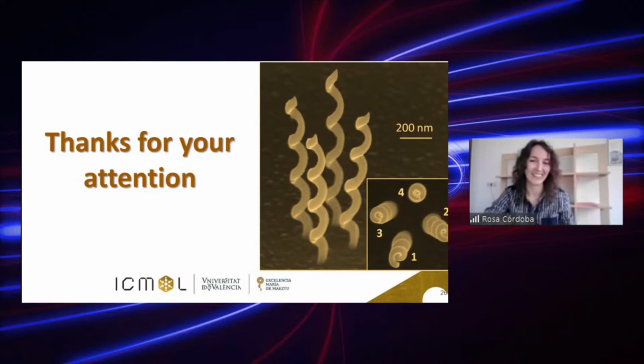So then do you know the penetration depth of any of your nanowires or your helices? The penetration depth, you mean from the superconducting properties? Yes, yeah. I mean, the coherence length was around 4.55 nanometers, and the penetration depth around 450 nanometers. Okay, so then I was wondering, when you apply a transport current, wouldn't you get a kind of self-field effect from the current that would end up effectively narrowing the superconducting region? And I was also curious if that was accounted for in these simulations. Yes. In principle, the coherence length and penetration depth are included in the simulation. Of course, any experimental data that we have is provided to the simulations we are implementing.